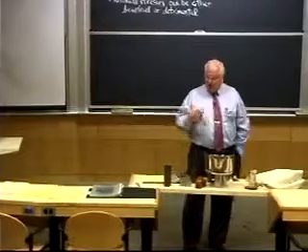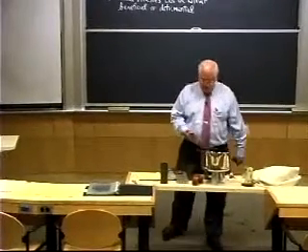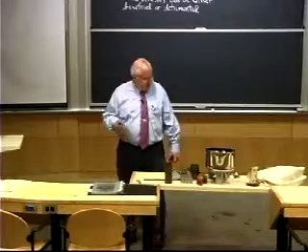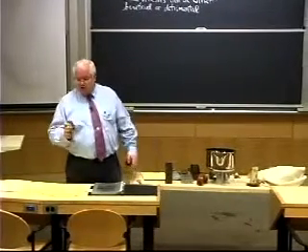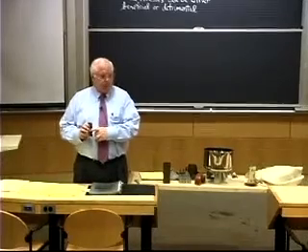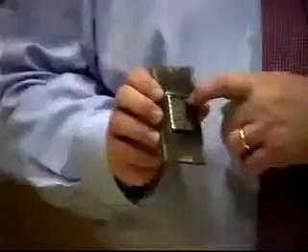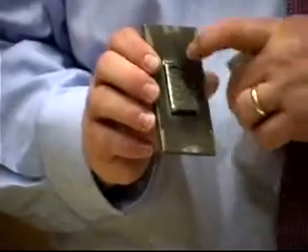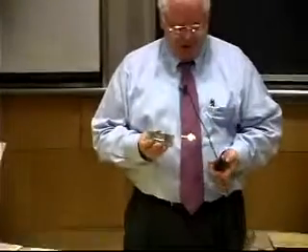So that's called solid freeform fabrication. It's been used with metals, and I have 2 examples made in my own lab. This is basically just an Inconel 718 that was electron beam melted back and forth. You can see the different texture on the surface, and just laying down a little wire and melting it, just back and forth, like the raster on a TV screen, and you can make up a pad of material.